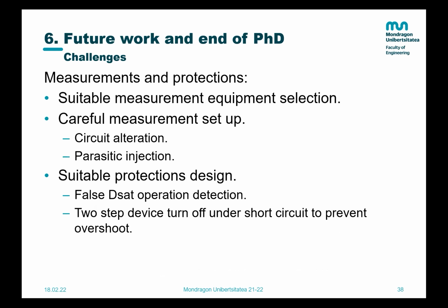And finally, you have to make sure that the measurements and the protections that you are using in your converter are suitable for silicon carbide. When we first started in our laboratory, I remember that I took the voltage probes that we had in the laboratory. Imagine we had 10 probes, 8 of them didn't work for silicon carbide. Their bandwidth was too low, so we couldn't measure our fast switching. The switching of the silicon carbide is very fast, so you have to measure even faster, of course.